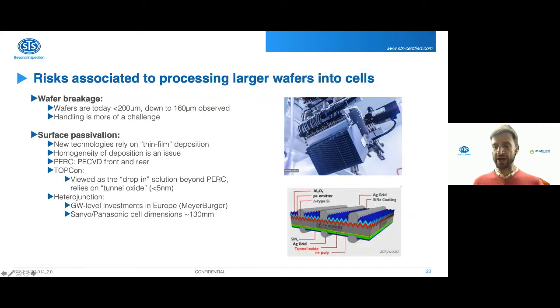Let's have a look at a few. I have 3 different slides which show the few risks that we have identified, which are described in this memo. So the first is all the risk associated with processing of larger wafers into cells. The obvious one is most probably the wafer breakage. If you keep the same thickness, or even go down in thickness to save material and to save costs, down to 160 micrometer, handling larger wafers becomes a challenge. Some of the tools are very advanced to handle large wafers, and it just becomes more and more challenging when the dimension is increased. Another risk is the surface passivation.